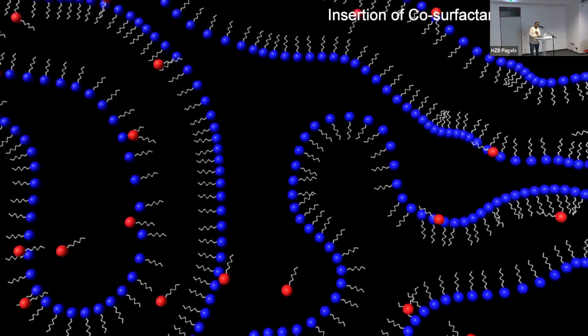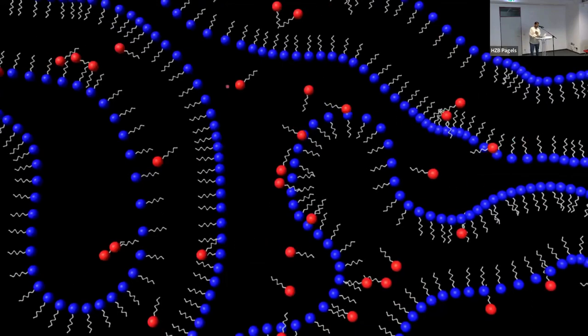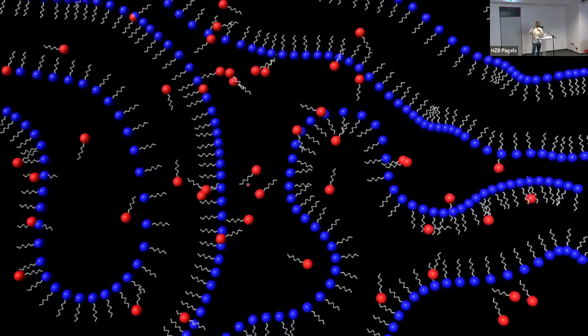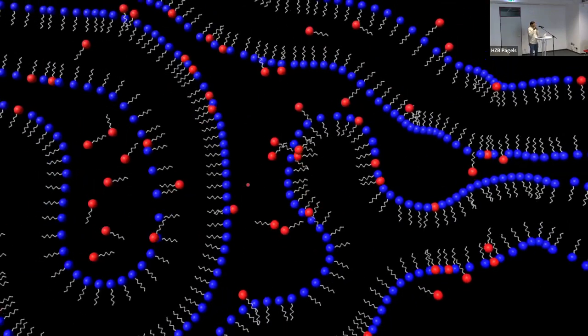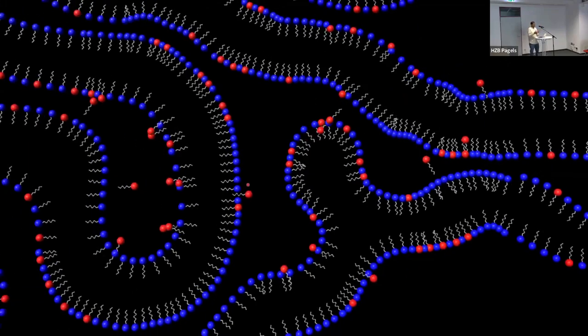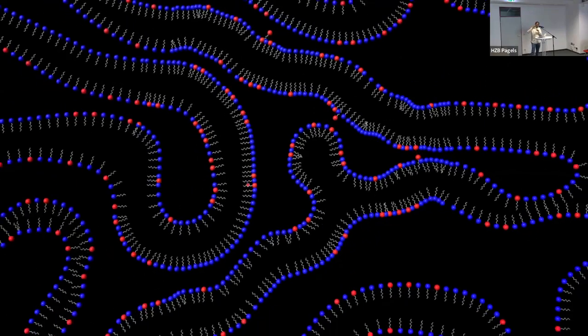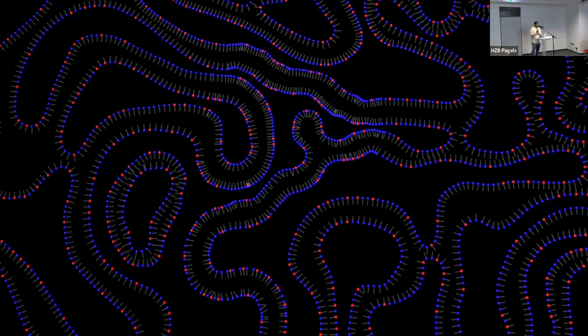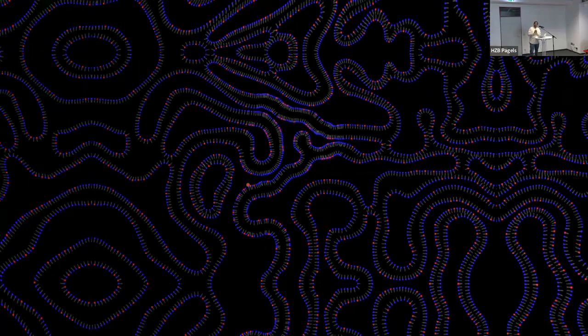And you can say that there could be repulsion between the quaternary nitrogens. So we added one more co-surfactant, which will go between these molecules and stabilize the interfaces, and those interfaces will allow you to grow the silica in them. And what we realized is that these are not floating flat in the solvent, but they are in the form of a droplet.